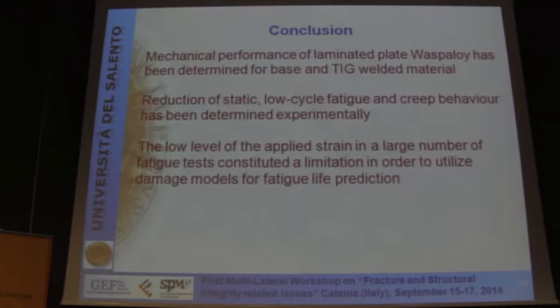In conclusion, we carried out several mechanical tests on a superalloy-based TIG welded material, and we determined the reduction of static, low cycle fatigue and creep strength. The low level of the applied strain was critical in order to apply several models to describe the damage model of the material. Thank you very much.